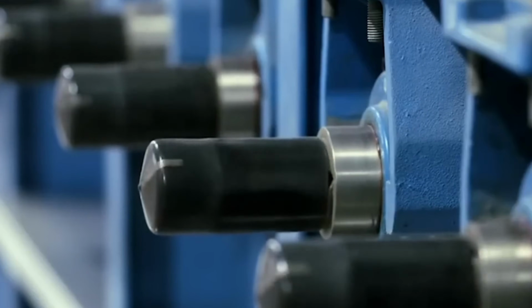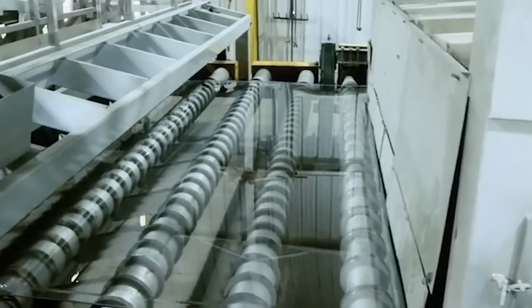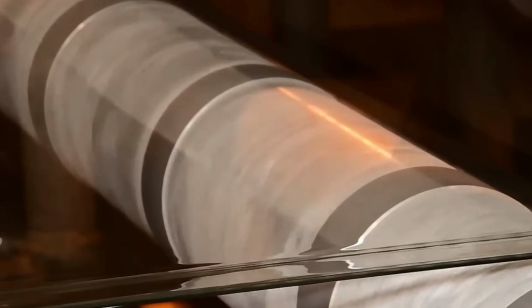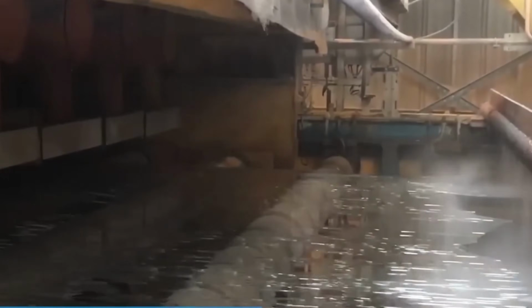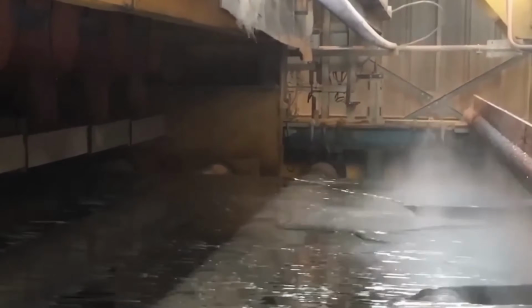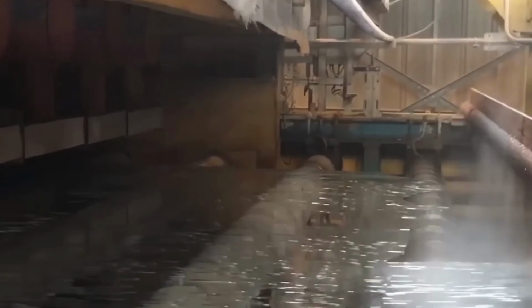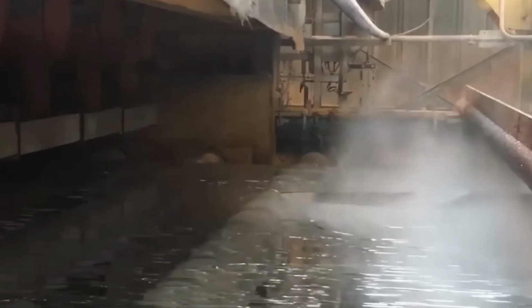The ribbon of glass gradually cools as it moves forward. Once it solidifies enough to handle, it leaves the tin bath and enters the annealing lehr, a long temperature-controlled tunnel that slowly cools the glass. Annealing is critical. If glass cools too quickly, internal stresses form that can cause cracking or spontaneous breakage later.